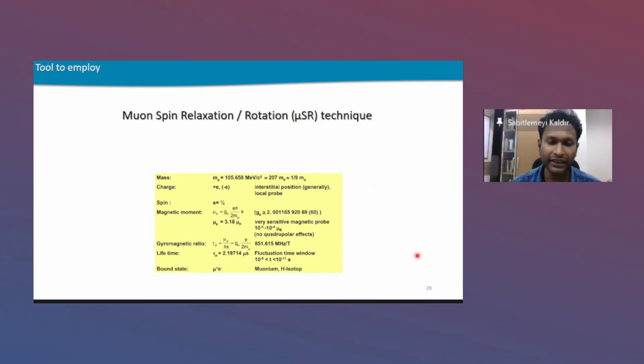As soon as I tell you that muons are spin half, you can easily recognize that it is very sensitive to the local magnetic field. As soon as the muons are placed in the interstitial position of the crystal structure, if there is a long range magnetic ordering, it sees the local magnetic field produced by the local moments around it. Okay, and as soon as it sees the local field, it starts to precess.